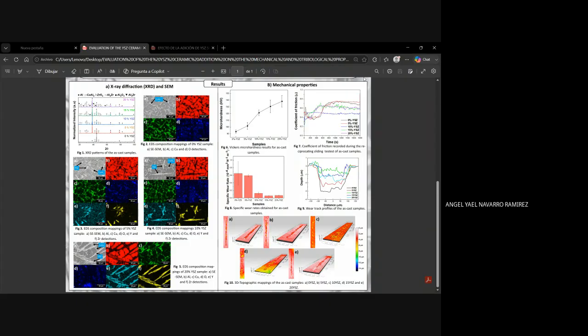Continue with figure 8. You can notice the tendency: the specific wear rate reduces when you add more YSZ. The sample with 15% has the lowest specific wear rate. What is the reason? The reason is that this composition didn't have the other intermetallic, the aluminum zirconium. This is the principal difference between 20% and 15%. The other phases and elements are similar, but this is the principal difference.